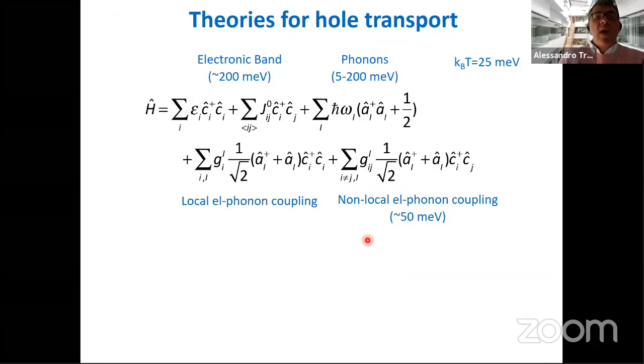As you can imagine, when you translate this idea into a model Hamiltonian, we saw them from Bernardi's talk yesterday and also from Oleg Prezhdo. This problem is very standard in the mathematical form, but it becomes non-standard if you put the numbers in it. What makes it non-standard is that the bands are very narrow and they have the same order of magnitude as the phonons that are strongly coupled to them, and they are not very different from the room temperature typical energies. Therefore, we have a situation where all matrix elements have similar magnitudes. We cannot really derive a nice perturbative approach to transport.